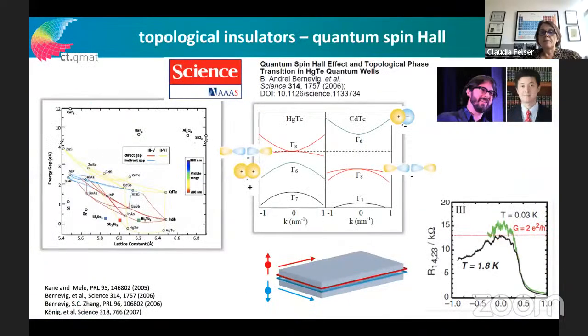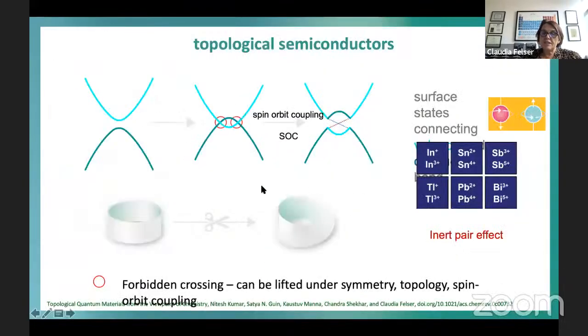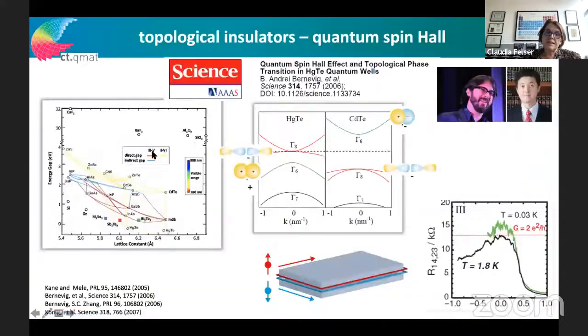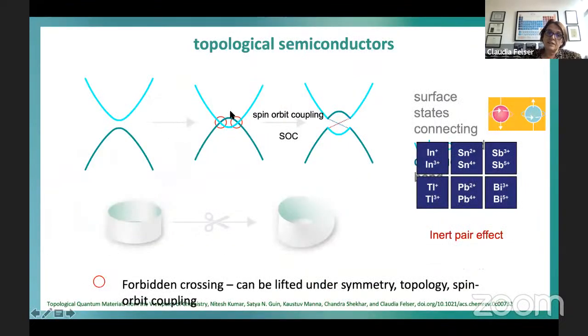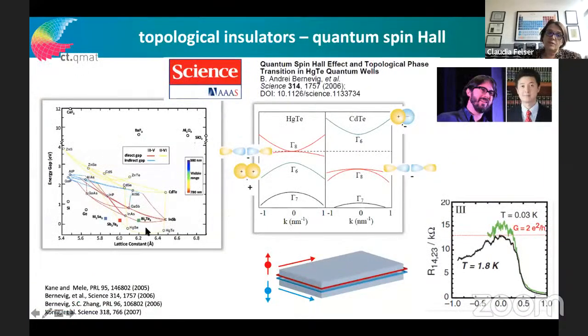But you can now do the same as I mentioned here: looking for some compound which has this overlap between the conduction and the valence band. And people have worked on solar cells for a long time. So you see you can have many binary semiconductors in the range of visible light, but there are also materials which have a small band gap or a negative band gap. And a negative band gap is exactly what we have here because we have this overlap. So therefore it was very clear that people looked for this negative band gap compound.